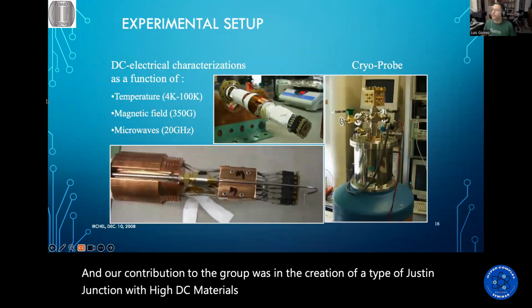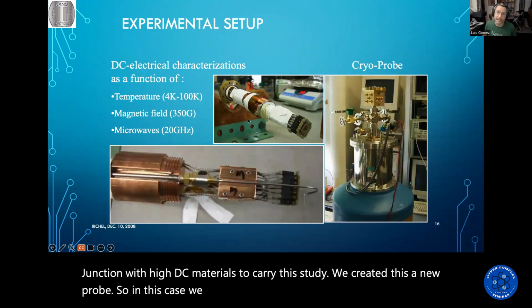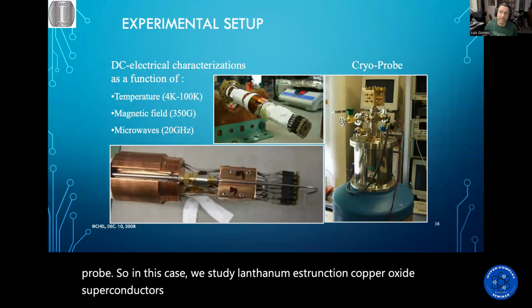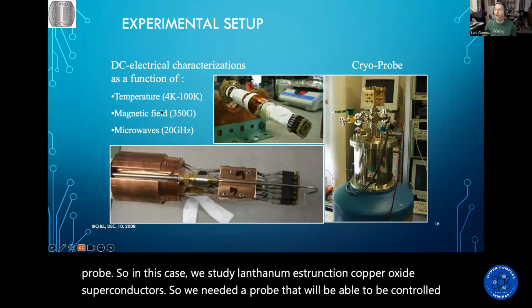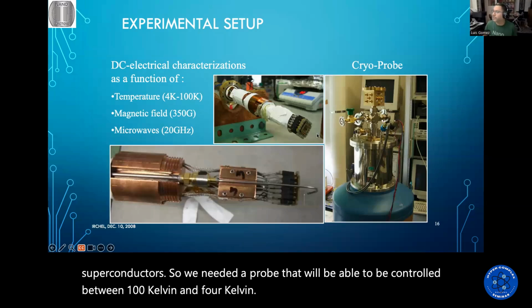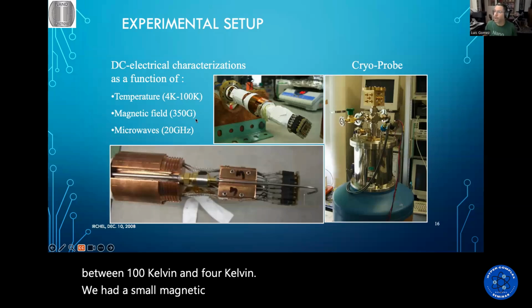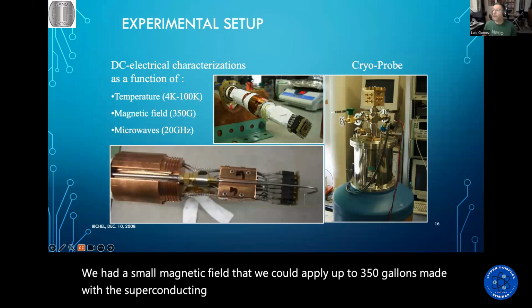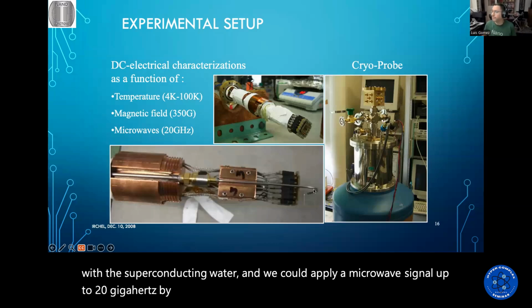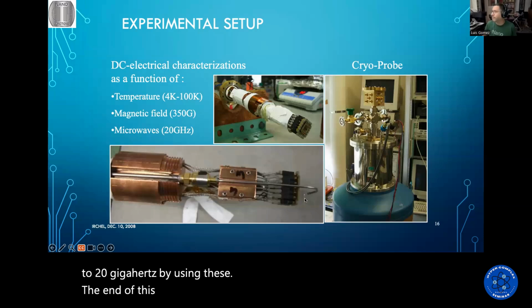To carry out this study, we created a new probe. In this case, we studied lanthanum strontium copper oxide superconductors, so we needed a probe that could be controlled between 100 kelvin and 4 kelvin. We had a small magnetic field we could apply up to 350 Gauss made with superconducting wire, and we could apply a microwave signal up to 20 gigahertz using the end of this waveguide.